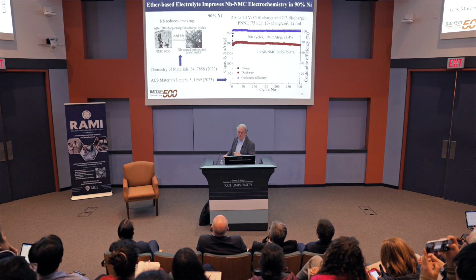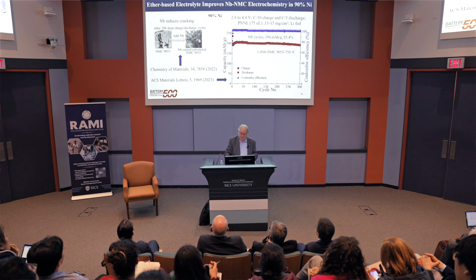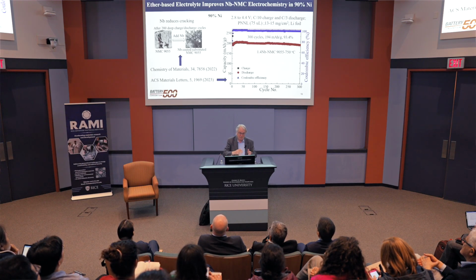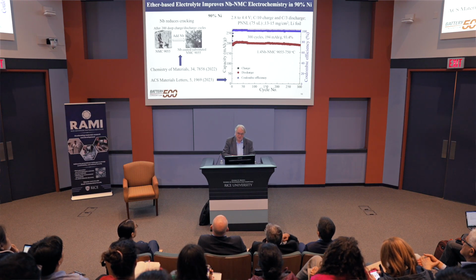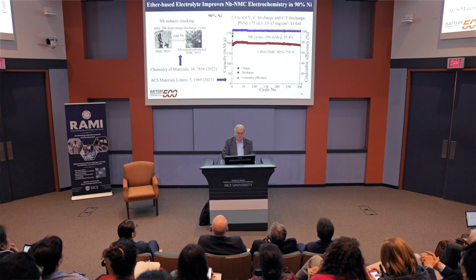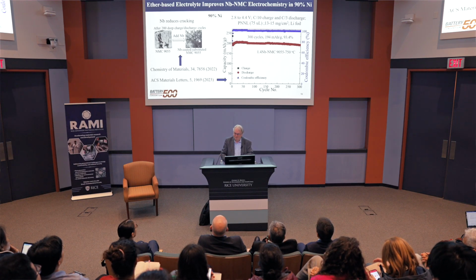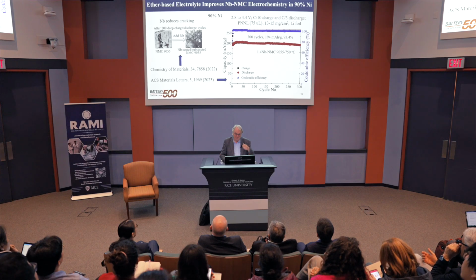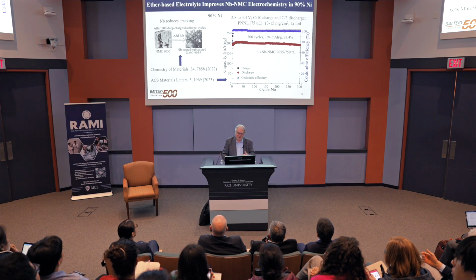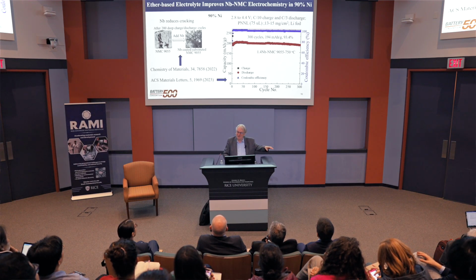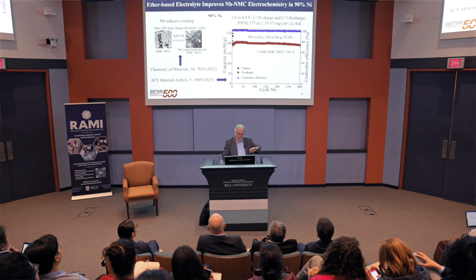This material now doesn't lose capacity over 300 cycles, even though it's 90% nickel. If it wasn't treated, it would lose the capacity after about 10 cycles. So it does make a huge difference, just these little tricks, which metallurgists learned years ago to protect iron and other things. Aluminum protects itself by making its own aluminum oxide film on top.